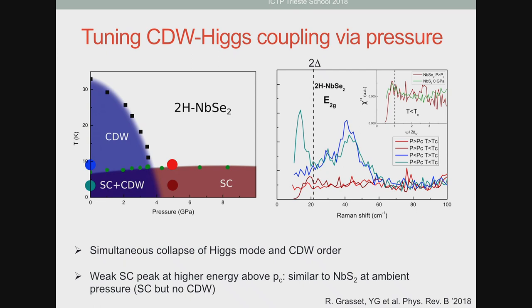Okay, but the key observation here is summarized in these spectra. In this scenario, the pair breaking peak is this one, in the red spectra, which are taken outside the coexistence region, at high pressure. This is above TC and below TC. This is this small thing. Once you enter the coexistence region, you have a sharp peak, and this sharp peak is below 2 delta. It's much sharper, and clearly we are not talking about the same feature as here. And remember, the TC is almost equivalent in both states.